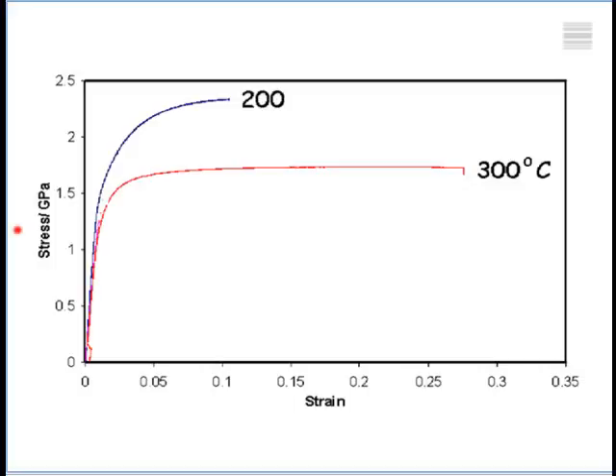So my question is, why do we have more ductility at 300 degrees centigrade transformation than at 200 degrees centigrade transformation? And I will show you some further data which are puzzling, that why do we have such a large variation in ductility depending on transformation conditions. Because in order to design steels, you need to have a good understanding of what's going on. Now, one of the clues on why this happens comes from a neutron diffraction experiment in which we pull the material inside a reactor so that we can follow the changes in phase fractions as we pull it.